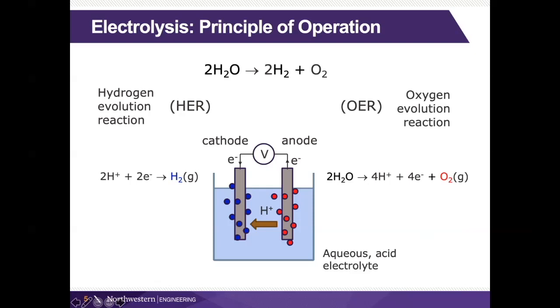And so if we have an acid electrolyte, as I'm showing here, although as Tom mentioned, usually if you have a liquid electrolyte, it's typically alkali, but the principles are similar. And this connects then to the polymer electrolyte membrane systems that Tom also mentioned. What we're doing here is providing the electricity, driving the hydrogen evolution by requiring the protons to react with the electrons here. That's the only way we're going to get current through this system. And then at the anode side here, we're evolving oxygen. So this is just the exact opposite of our fuel cell. And again, using a liquid electrolyte, because the oxygen and hydrogen are produced as gases, we might introduce a diaphragm here to keep the two chambers separated from one another.